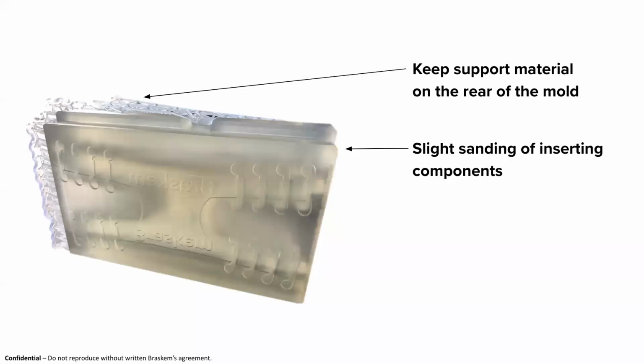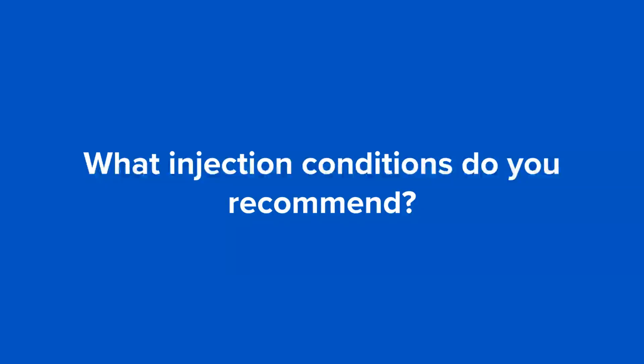We were getting very thick cross sections, which required a lot of curing, and that curing can happen unevenly in some instances. So you can get warpage. In our case, the warpage was extremely minimal. To get the tolerances to fit into our metal mud mold, if you will, we just required a slight bit of sanding to be able to make that fit a little more snug. Good.